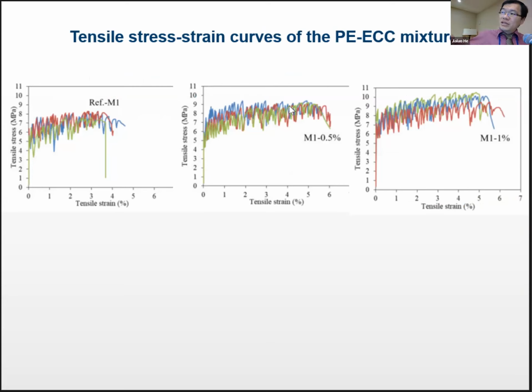Now, again, this is not your traditional concrete. That's why you're seeing this kind of strain hardening behavior. The reference M1 is the one without any nanosilica, and then 0.5% nanosilica, 1% nanosilica. You see this kind of tensile behavior. But from the M1, the reference one, we can see that, well, it's not a very good ECC because you're not achieving really good ductility. In that case, it basically indicates you either need a weaker matrix or stronger bond between the fiber and the matrix. So again, it's a balancing act.